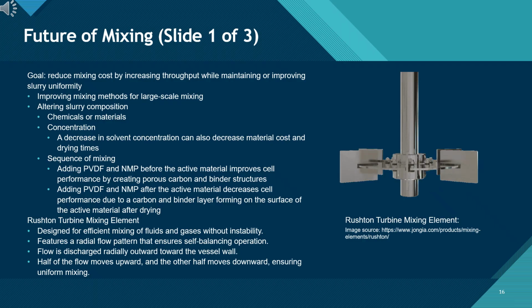Future of mixing. Slide 1 of 3. This slide highlights the goal of reducing mixing cost by increasing throughput while keeping slurry uniformity high. Improvements focus on scaling up mixing methods and optimizing slurry composition, such as reducing solvent content to lower material cost and shorten drying time. The sequence of ingredient addition is also important.